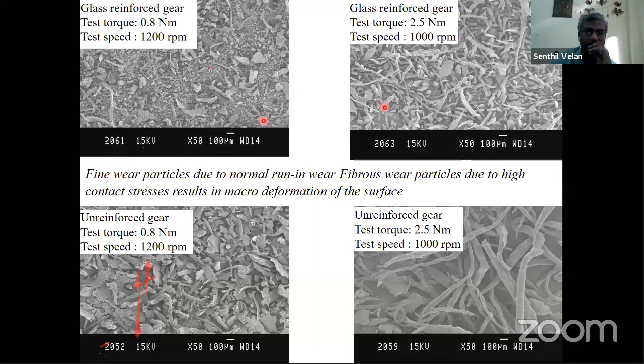So this is about contact stress, where you will be able to see that there is a fine particle due to the normal run-in wear, but when you cross the critical contact stress, you will end up getting a fibrous wear particle. This is like your run-in wear. This is acceptable, it is not going to cause any issues. So you have to decide our critical load so that you avoid this particular class of thing. And surprisingly, you will see no big difference between these two also, unreinforced and glass reinforced material.